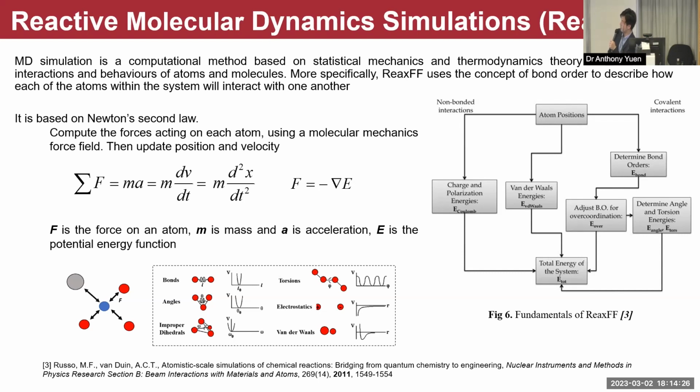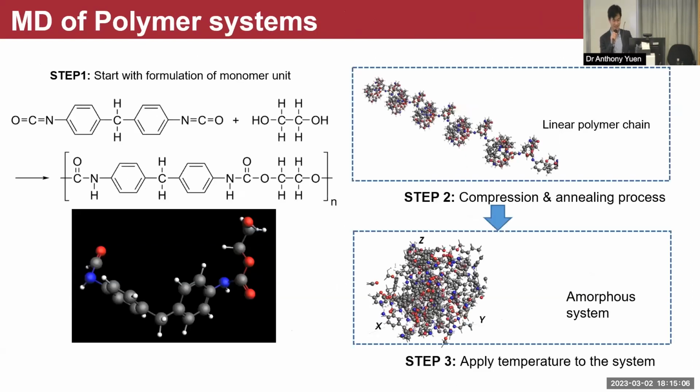So what it does is go through the provided ReaxFF reaction table for a specified set of elements. Say if we pick C, H, and O, then we iterate through the energy. Once we solve it, we solve the bond order and bond angle to govern whether this is a single bond, a double bond, or so forth. Once we decide that, we can iterate through the steps and conclude whether a breakage will occur or a bonding will occur based on the evaluation.